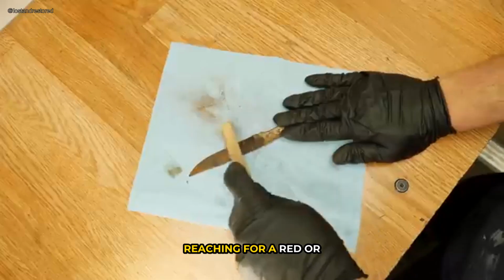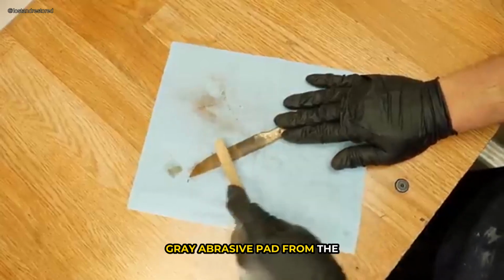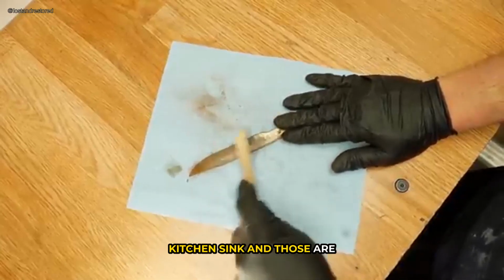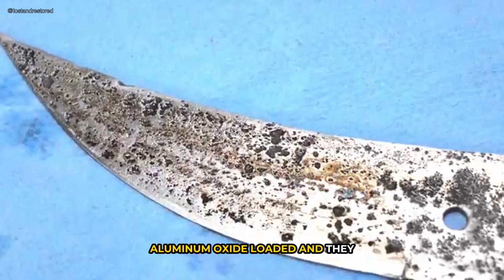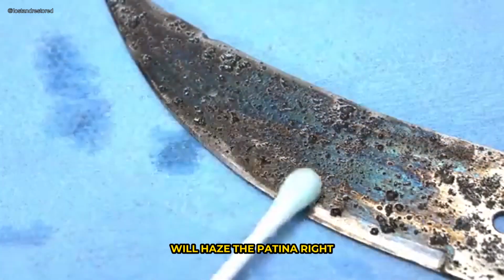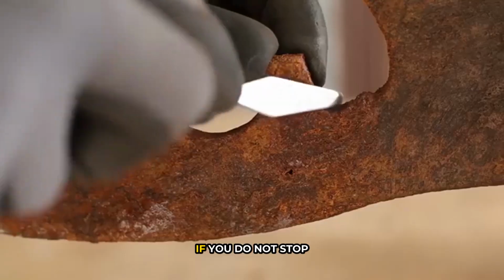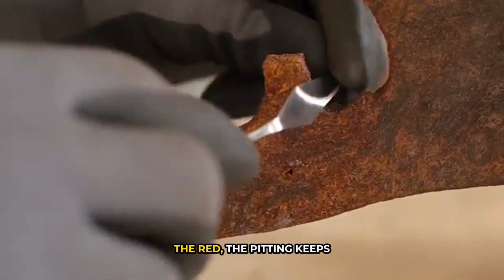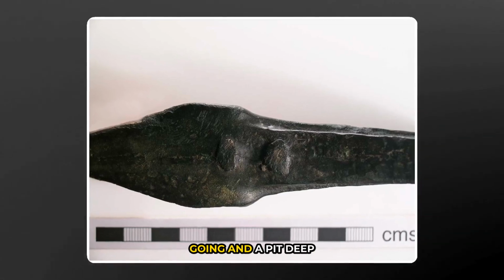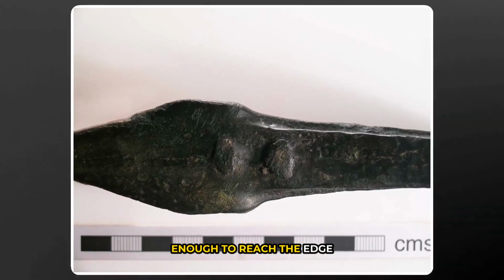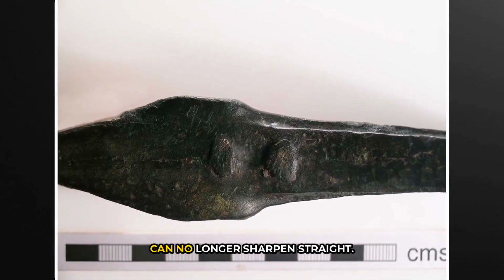The error here is people reaching for a red or gray abrasive pad from the kitchen sink, and those are aluminum oxide loaded, and they will haze the patina right off in 3 passes. If you do not stop the red, the pitting keeps going, and a pit deep enough to reach the edge bevel is a blade you can no longer sharpen straight.